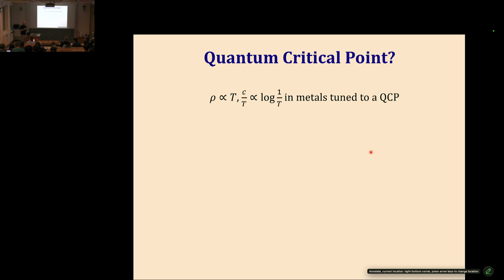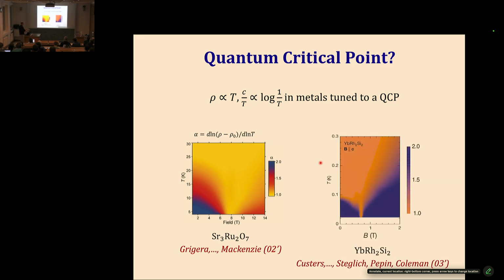Another example is in heavy fermion systems, where the system is just on the verge of undergoing a transition between a large Fermi surface and a small Fermi surface. Something special has to occur exactly at the border between the two. And it turns out that, again, in many cases, not universally, you find that exactly at the transition point, you have a linear in T resistivity that extends all the way down to the lowest temperatures. When you tune your parameter, and in both of these materials, the non-thermal parameter you tune is magnetic field.